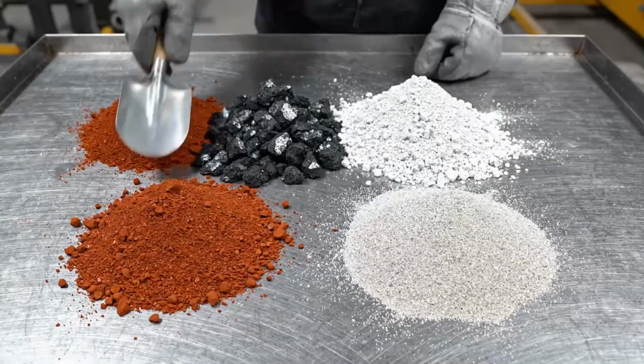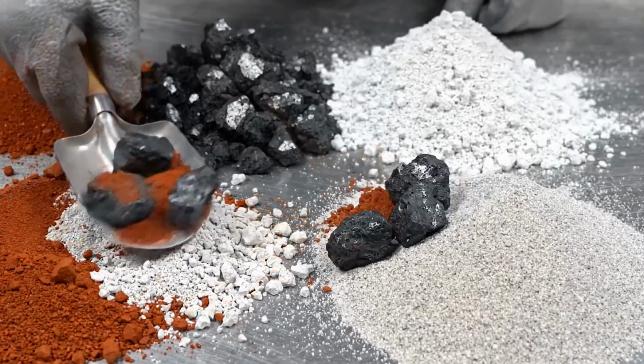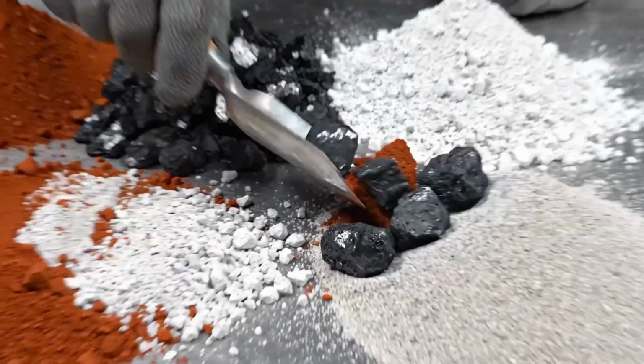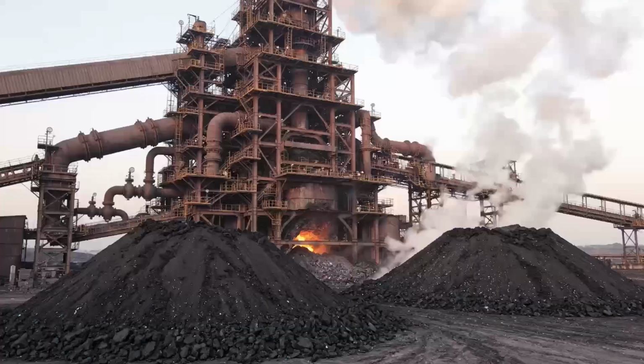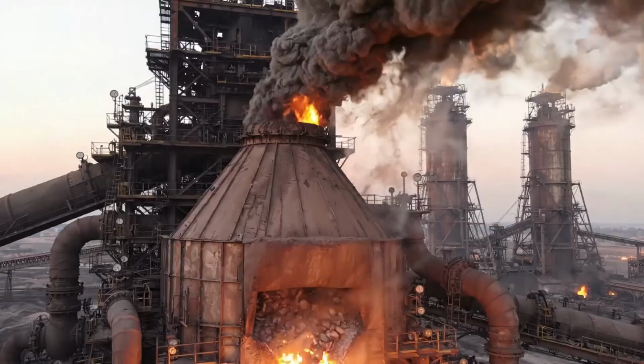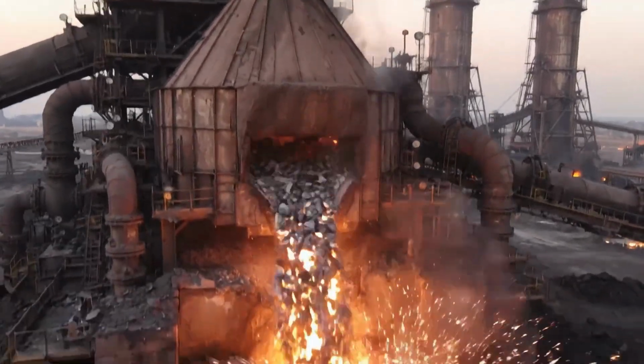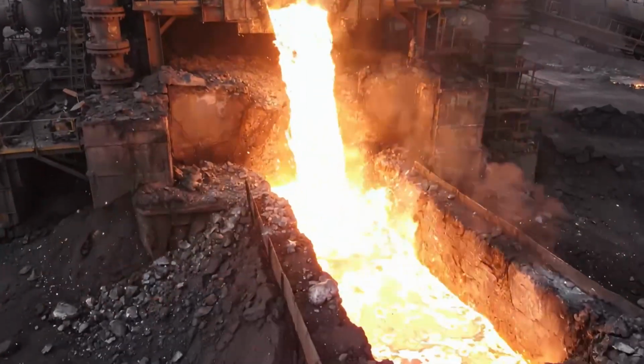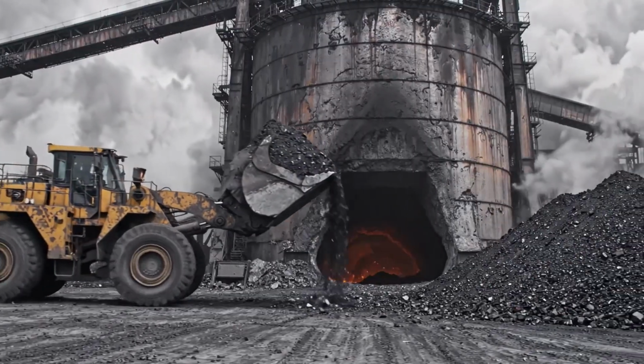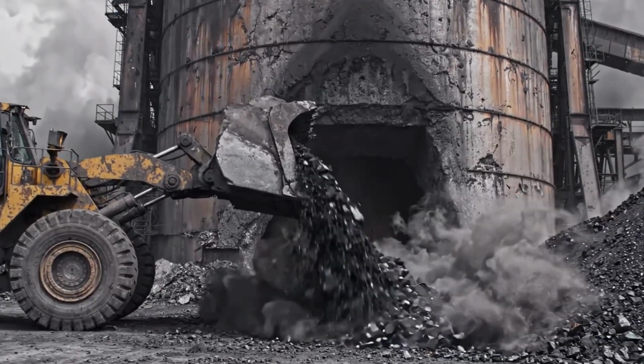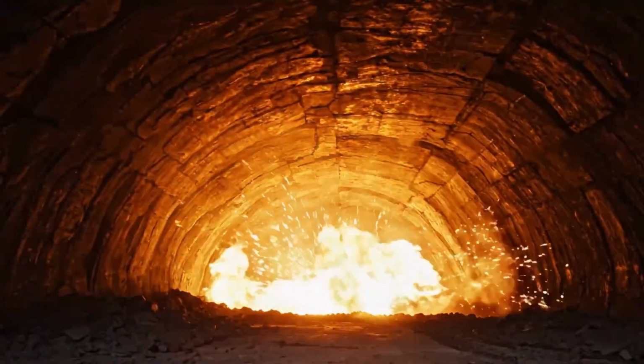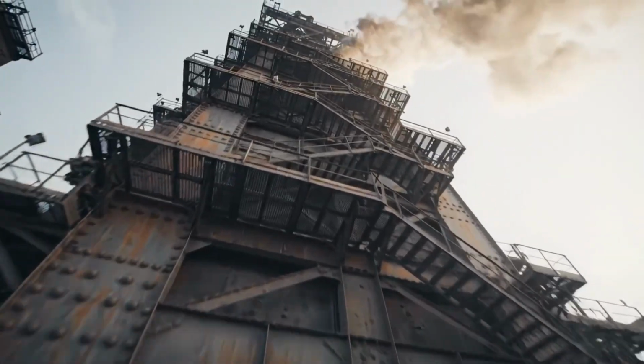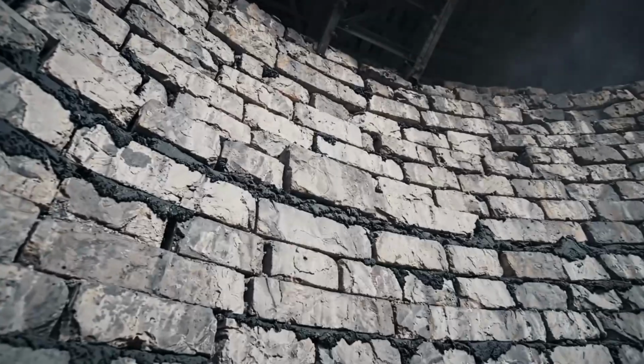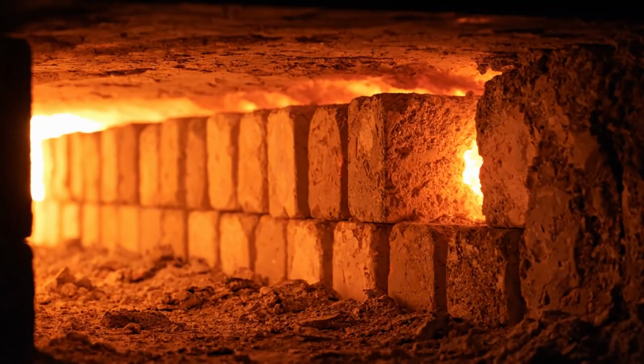Inside the furnace, temperatures reach 1200 degrees Celsius. At that temperature, the carbon in the coke undergoes one of the most elegant reactions in extractive metallurgy. It combines with the oxygen in the iron oxide, seizing it with a superior chemical affinity, and escapes upward as carbon dioxide. The iron, freed from its bond with oxygen, melts instantly and begins to accumulate in the crucible at the bottom of the furnace, where it gathers in a lake of molten metal that grows hour by hour, invisible from the outside, but measurable by the monitoring instruments.